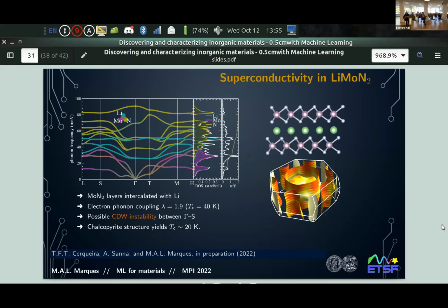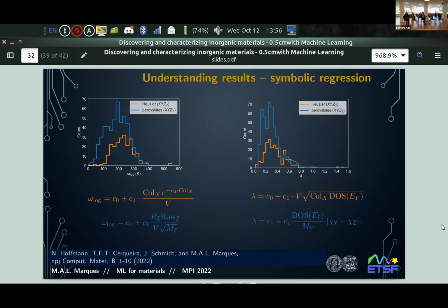The second problem is that experimentally, this was synthesized only twice. And the first time they claimed that they have alloying between the molybdenum and the lithium. And that again decreases the density of states at the Fermi level and will probably decrease superconductivity. But this is the kind of thing that you find out just by searching, right? That is almost at the end. This is, I think, my last slide.